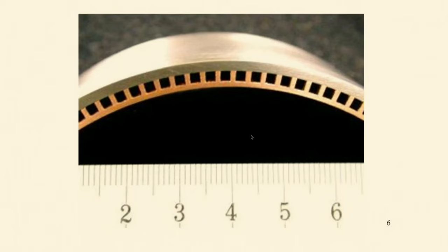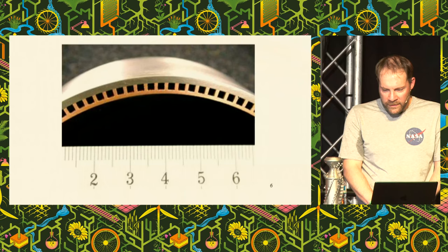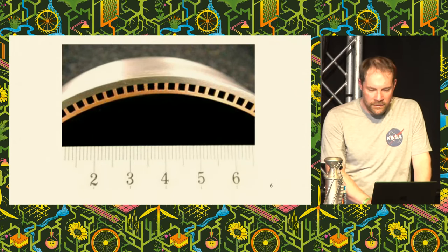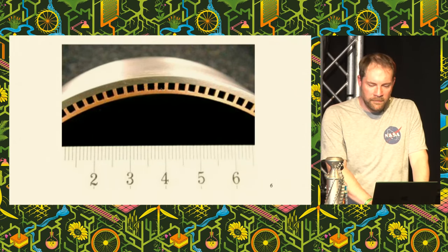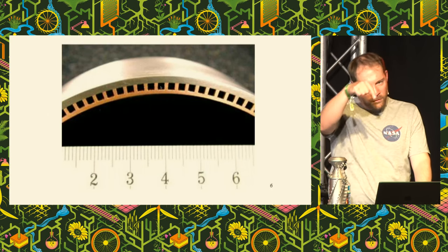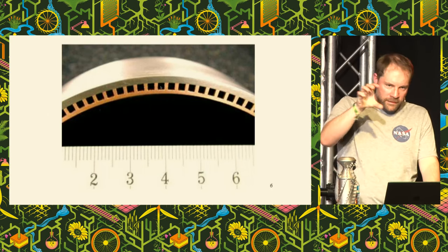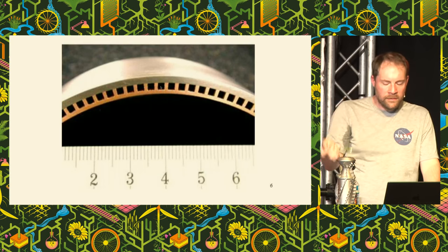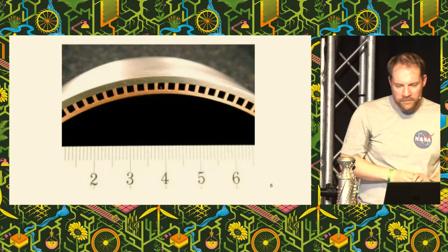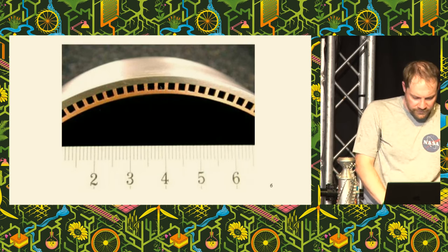So the way you make these is you start off with a huge lump of copper, and you machine a big hole in the middle to get the inside diameter of the combustion chamber you want. And then you turn down the outside to get the outside diameter of this copper fin part that you need. And then you put it up on another machine and start milling channels all the way through the contour of the rocket engine. Turn it around a bit, do another one, turn it around a bit, do another one. This can all take days to weeks, as you can imagine.